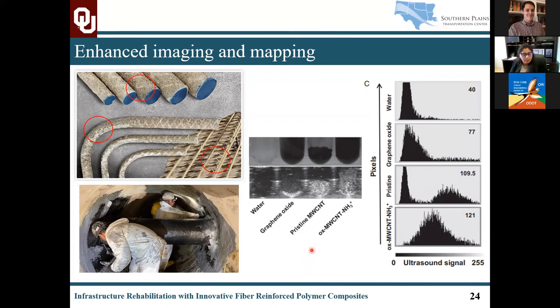And what happens with these carbon nanotubes is they improve the echogenicity of any solutions that can be incorporated with them. For example, if we see this particular picture where we are using water, graphene oxide, pristine, and modified functional group MWCNTs and with ammonia, we see that the ultrasound signal is very high in these nanomodified solutions with carbon nanotubes. This can help us improve the imaging process that there is right now and also add to the capabilities that we have for non-destructive evaluations.